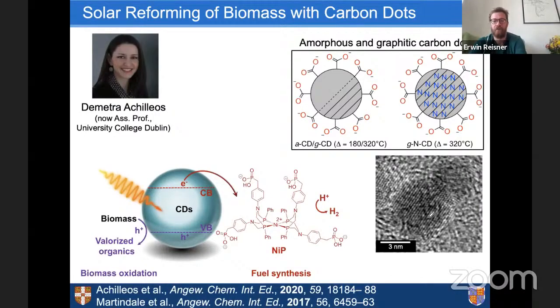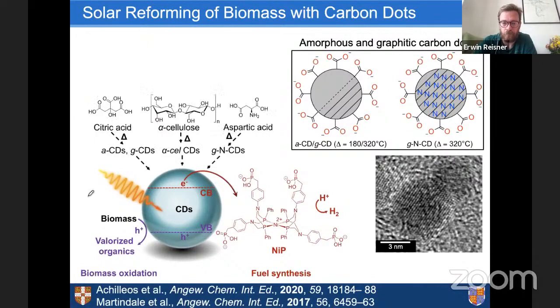what you can see here by the TEM image with the fringes nicely shown. So the idea was now, with these photocatalysts that we have been developing for a couple of years, in fact, this was work by Benjamin Martindale. He really brought them to the lab with Georgina Hutton. We could show that these carbon dots are really nice photocatalysts under sacrificial conditions to make hydrogen with this nickel catalyst. So Dimitra took on this work to show that we can indeed also use this for biomass conversion.